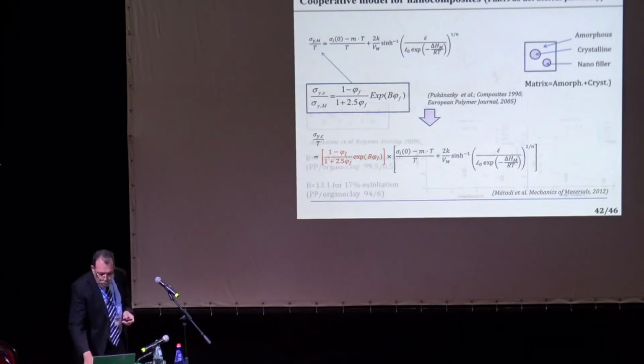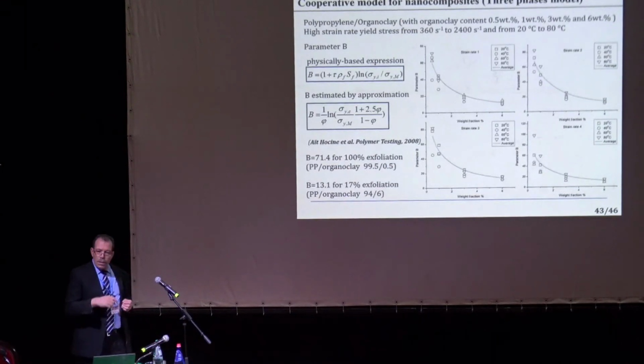Okay. So we use this in an inverse way. We did experiments for, which material here? I think we did some experimental work with polypropylene filled with the nanoclay, and this is what we get. We're looking into different strain rates, but we just choose one. It doesn't matter which one. These are 4 different strain rates. So we choose one. As you can see, this is the parameter B that we calculated through this relationship here as a function of the weight.